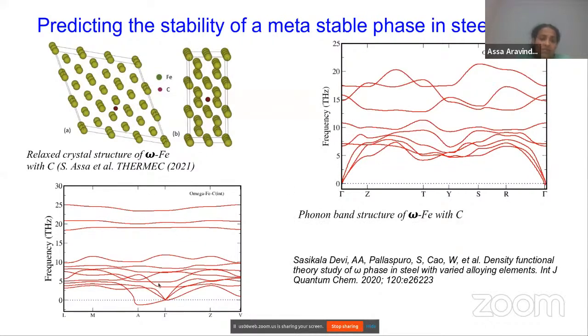But here you can see that when it is in the interstitial position, largely it is positive, but we can see that there is a negative mode coming in. So this structure is not stable. So using DFT, we can verify these kinds of facts. We can study the phonon band structure and see whether it is stable or not.